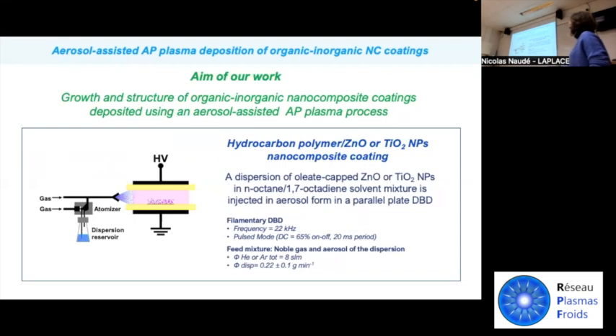In our process, a dispersion of oleic-capped zinc oxide or titanium dioxide nanoparticles in a hydrocarbon solvent mixture is injected in aerosol form in the DBD. The capping is just to achieve a good dispersion and to disperse the metal oxide nanoparticles in apolar solvents. The plasma was operated in a classical filamentary regime, and the main gas in this case was helium or argon, so a noble gas. And the plasma was operated in pulsed mode.